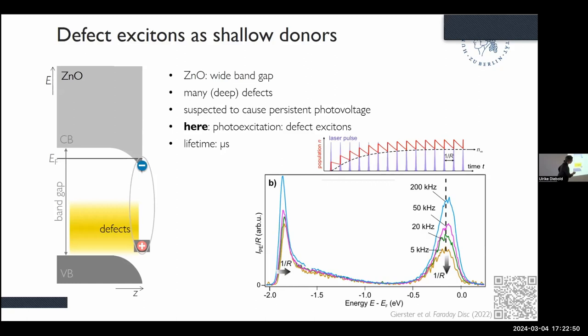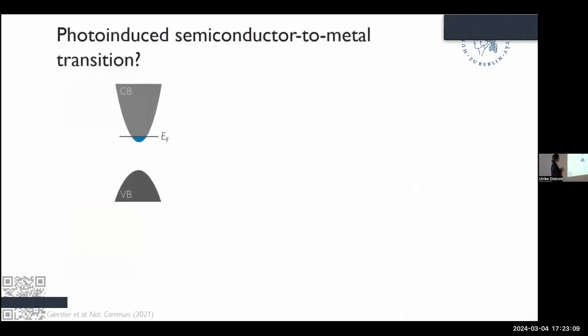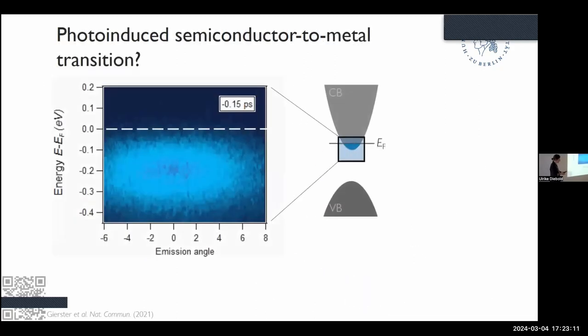Here with 5 kilohertz, we have 200 microseconds that the defect excitons have to decay. And for 200 kilohertz, they are probed after 5 microseconds. So the signal is higher. Anyway, so we have defect excitons. They have a long lifetime. Can we now use these defect excitons to change something about the electronic properties of zinc oxide?